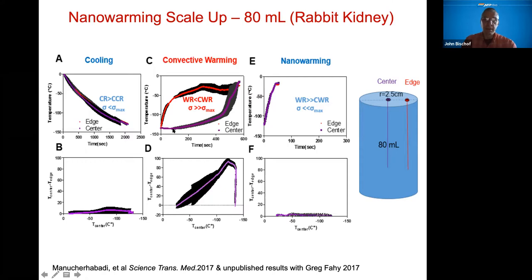And then we looked at, if you convectively warm, you come up fast on the side, but you lag in the center, just like the ice cube, and you get these huge temperature gradients. And in fact, in many cases, we crack. If we nano warm, you can see that both the edge and the center are coming up uniformly and there is no thermal gradient. So this is sort of the demonstration that this is working from a heat transfer point of view.